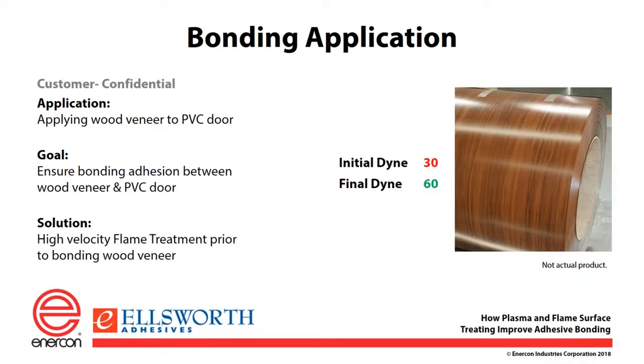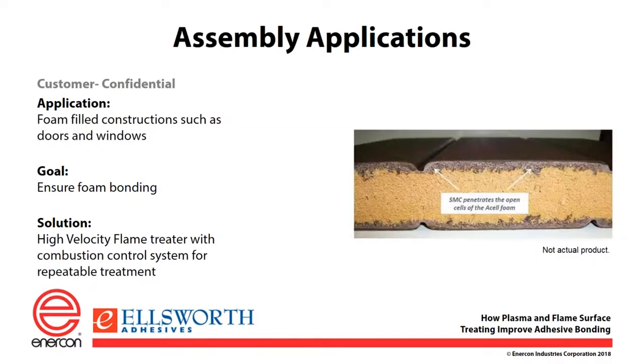PVC door, wood veneer to a PVC door. They're almost always pre-treated with flame in order to increase that dyne so that you can get, again, the coating, and it'll stay, a long-lasting coating of the veneer. And then assembly applications, this is just showing a foam-filled construction in order to make sure that we have a good bond on the outside, and that stays on the outside. It is usually a flame treat prior to the coating going on.